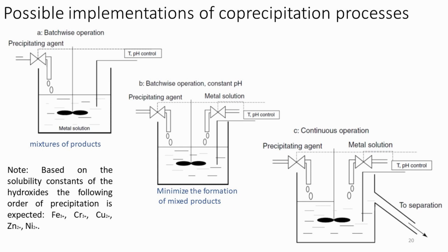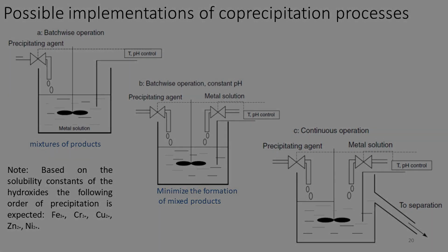To minimize the formation of mixed products, the preferred method is to operate at constant pH by using a simultaneous addition of reactants. However, even using this mode, mixtures are produced because the change in liquid volume in the reactor changes both the concentration of the reactants and hydrodynamics. A further improvement is to perform the process continuously.